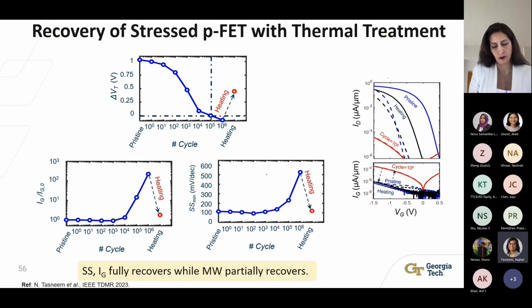Now, interestingly, after thermal treatment, the memory window partially recovers, as shown in the previous slide as well. However, what is interesting is that both the gate leakage and the subthreshold swing fully recover after this thermal treatment and go almost to their pristine state.